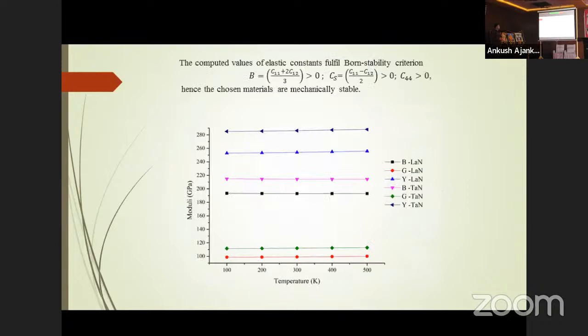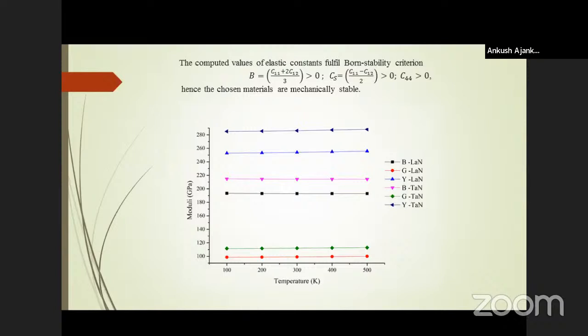The computed values of elastic constants fulfill the Born stability criteria given by these relations, and hence our chosen material is mechanically stable. Further, in this plot, I have plotted the values of bulk modulus, shear modulus, and Young's modulus. From this graph, it is clear that the Young's modulus of tantalum nitride is greater than that of lanthanum nitride. It implies that tantalum nitride is stiffer than lanthanum nitride.